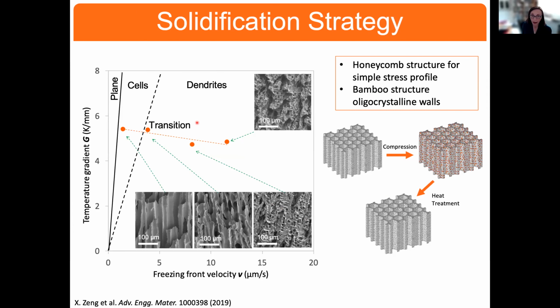And again, we could do this in one of two ways. We could take our microstructure map, temperature gradient, freezing front velocity that I've shown you before, and work our way over, work toward this cellular structure. And you see these materials here as they go from highly dendritic to almost cellular.